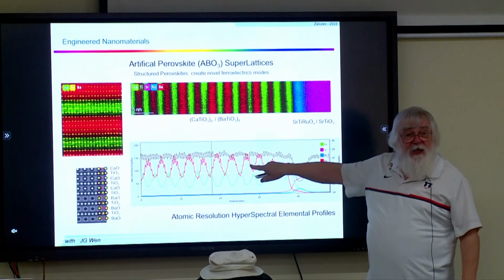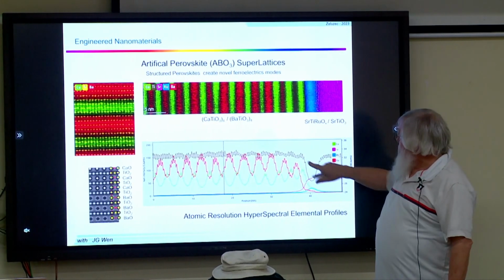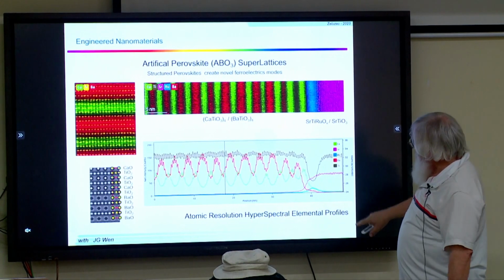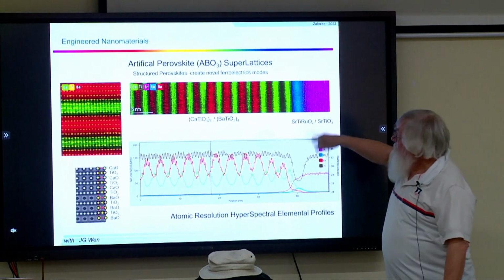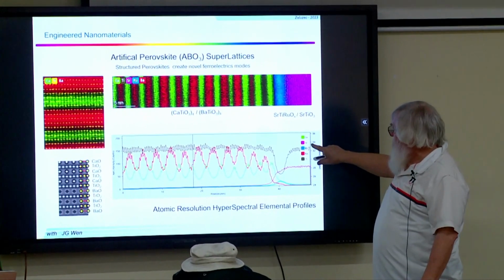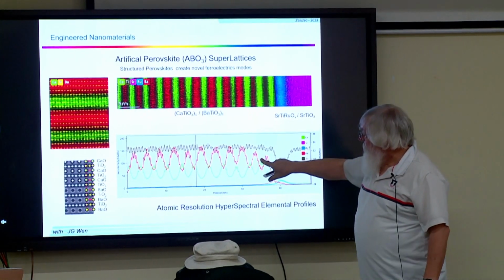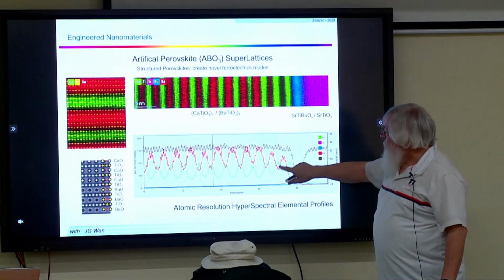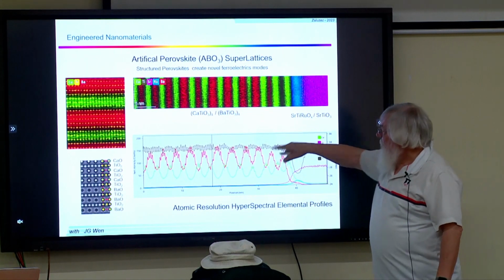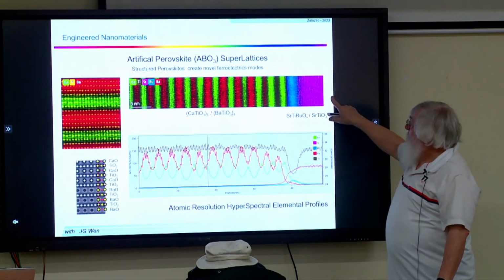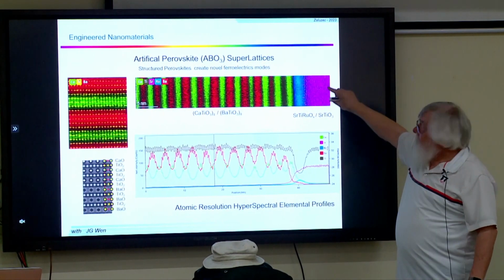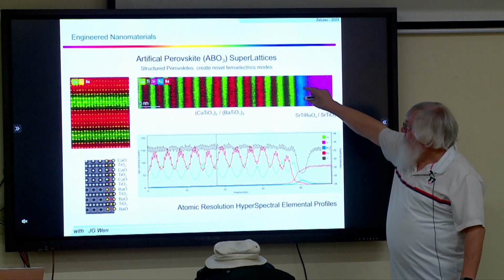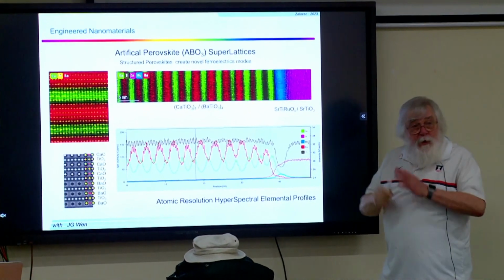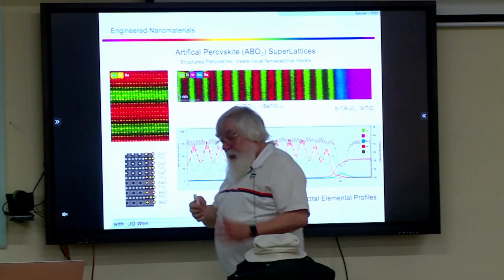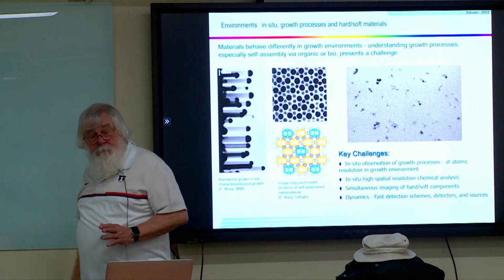The wiggles that you see are real. We're seeing, let's see now, I have to look at the color code here, the titanium elemental distribution across the planes. The barium and the calcium, you notice they oscillate. The titanium goes through everything. And down across here is the support material that's grown in, the strontium titanate and the strontium titanium ruthenium oxide. So we can characterize all of that and now begin to understand what's going on.